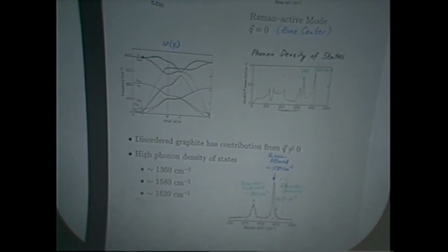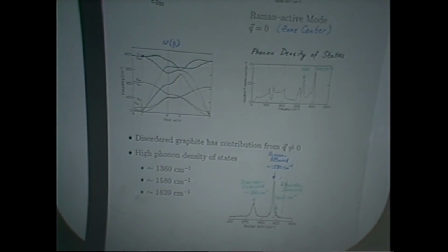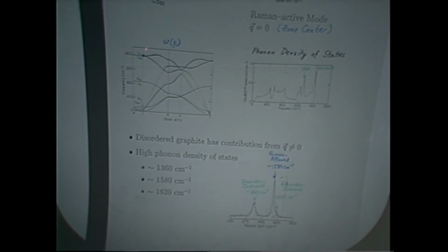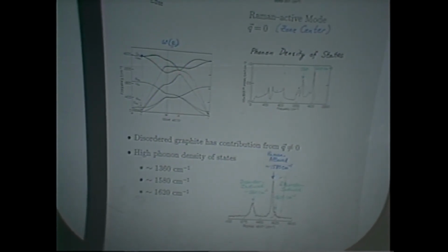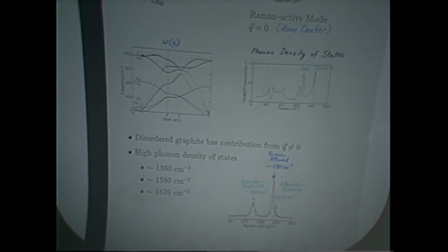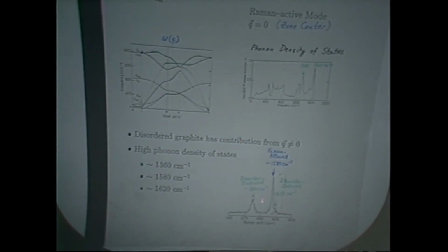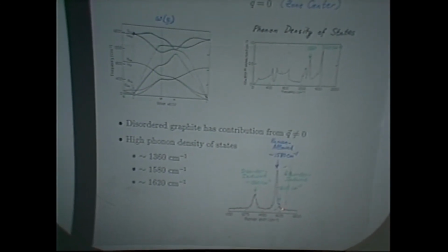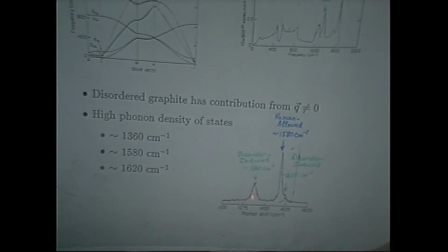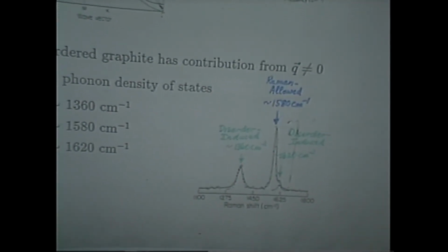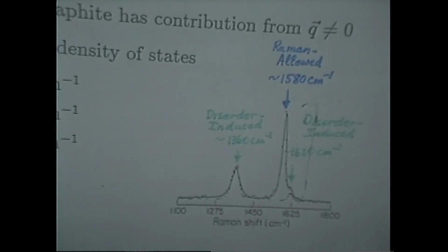However, if you have a disordered material like a carbon fiber, then you get contributions from other phonons, from those regions of the phonon density of states where you have a lot of phonons having the same energy. Here's one, the maximum here, and here's another one. And those are the ones that show up. It turns out that those particular modes, which I put in green, have a high electron-phonon coupling, so we see them. Here is a disordered mode, and here's another little one. By measuring the relative intensity of these disorder-induced modes that wouldn't be there if we had a perfect material, we have a way of characterizing the perfection of a carbon. And a fiber is an example of this.